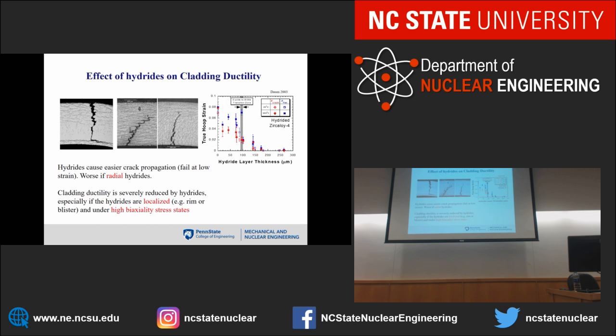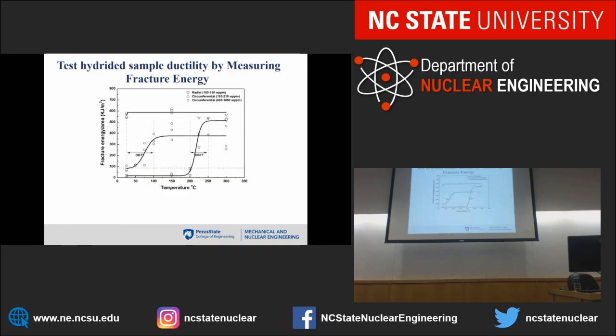This is a thesis of Rob Dahl a while ago. You can look at the hoop strain along, if you have a hydride layer thickness, rim thickness, and basically there's no ductility after about 100 microns. So the cladding ductility is severely reduced by hydrides, especially if the hydrides are localized or if I have a high biaxiality stress state. And this shows the fracture energy